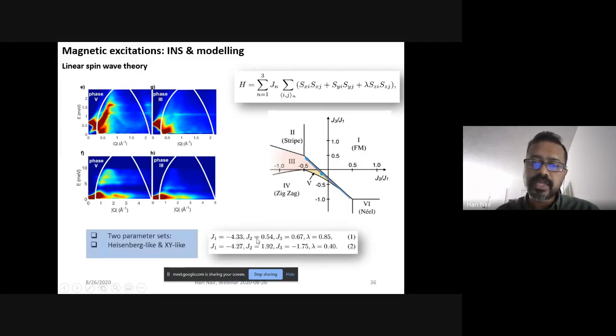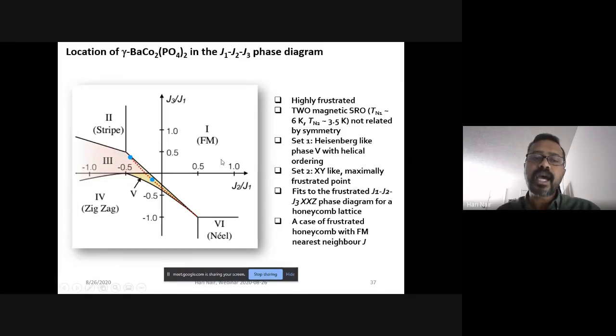Now, if we have these specific values, J1, J2, J3, and lambda, which is a parameter that combines these, for two different sets of J values, we get remarkable matches between the experimentally observed and the simulated patterns. So it leads to slight confusion, because one of them is more Heisenberg-like and one of them is XY-like. So we are unable to pinpoint if it is a purely two-dimensional system, because one of the Heisenberg-like systems also conforms to the simulated pattern matching with the experimental data. So that's slightly inconclusive.